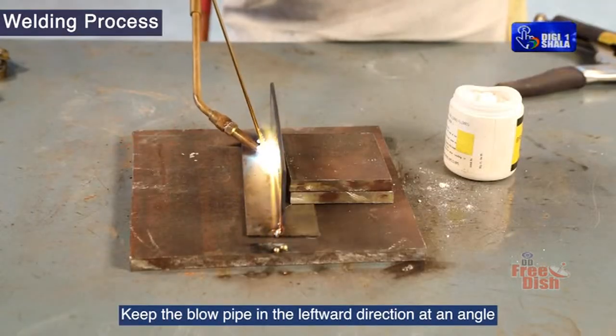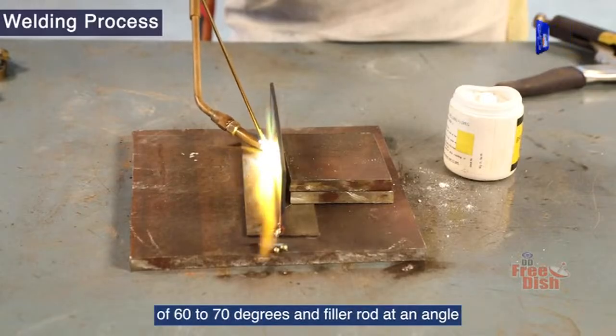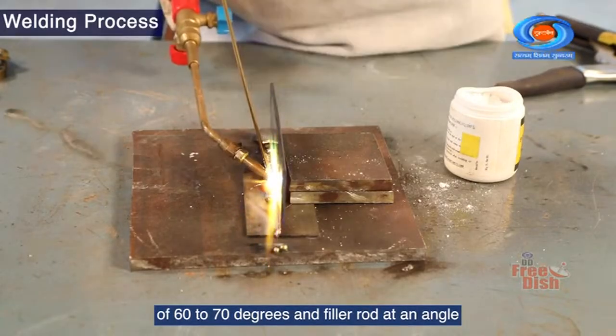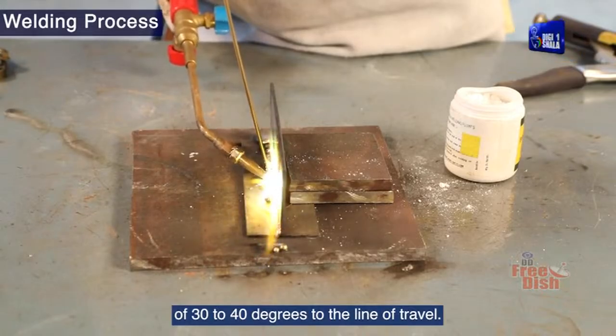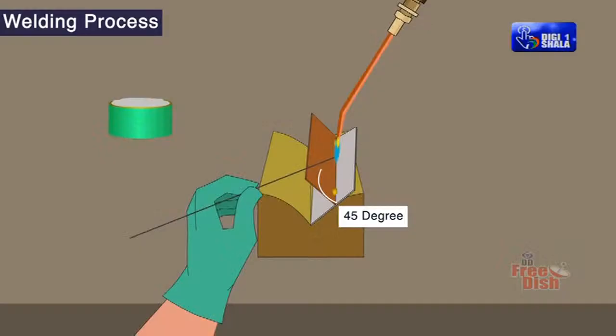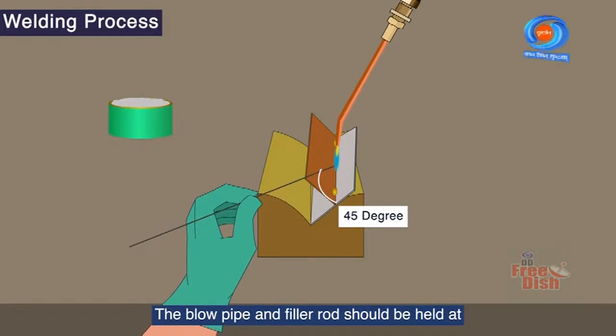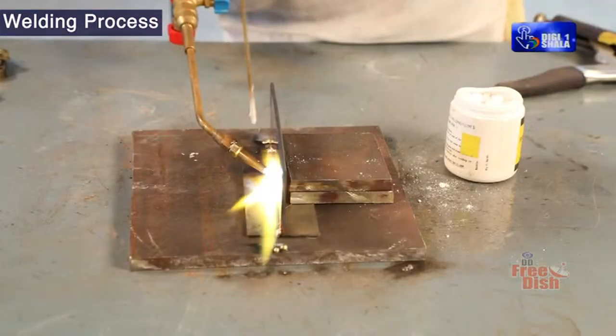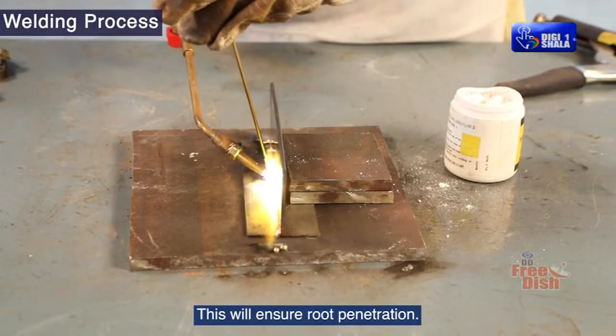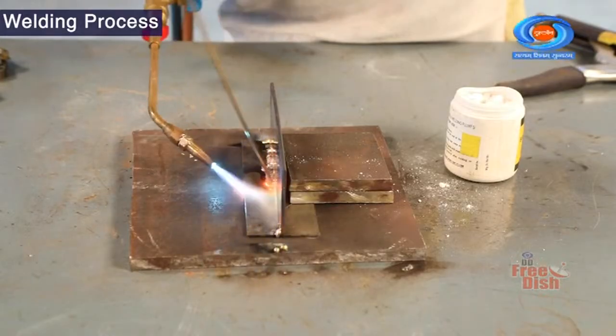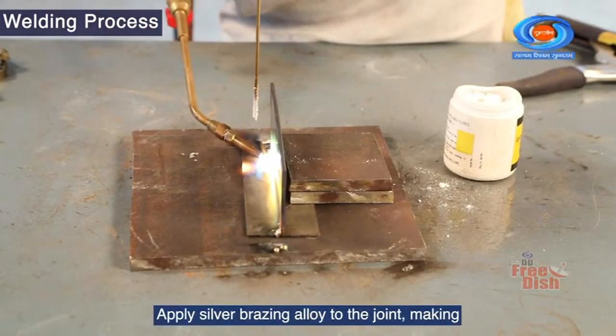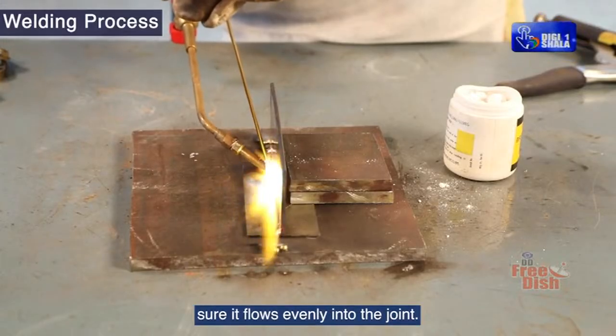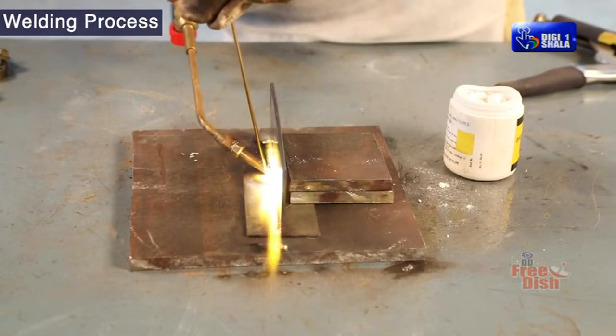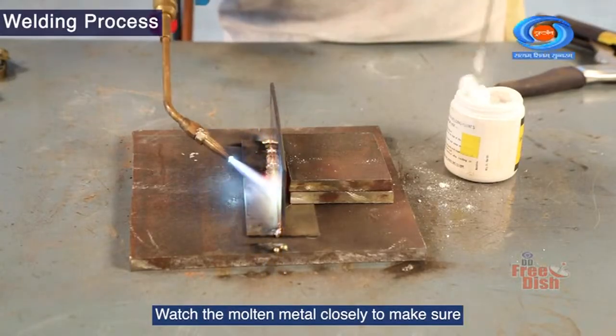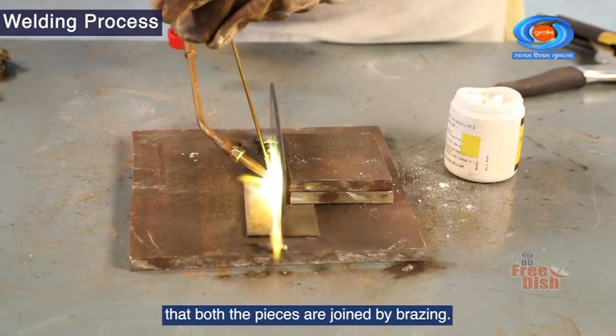Keep the blowpipe in the leftward direction at an angle of 60 to 70 degrees and filler rod at an angle of 30 to 40 degrees to the line of travel. The blowpipe and filler rod should be held at a 45-degree angle between the joint's two sides. This will ensure root penetration. Apply silver brazing alloy to the joint, making sure it flows evenly into the joint. Watch the molten metal closely to make sure that both the pieces are joined by brazing.